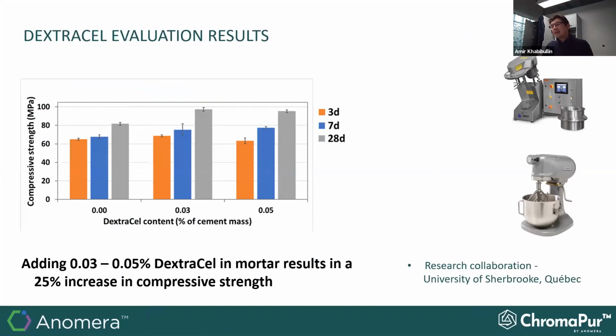And indeed, in our time with the LH accelerator, we managed to lower the DextraCel loading. The fact that DextraCel acts on a nano level means that you need a very, very small amount of the material to get a functional improvement in concrete. And we managed to lower the DextraCel load to just 0.03% compared to the weight of the dry cement to see the 25% increase in the compressive strength in the mortars.